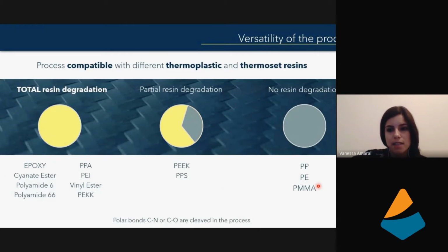Actually, what happens is that the chemicals are going to cleave the carbon-nitrogen or carbon-oxygen bonds in the matrix. So the process works very well. It's very compatible with epoxy resins, cyanate ester, polyamide, PPA, PEI, vinyl ester, PEKK, and other types of thermoplastic and thermoset resins. Using PEEK and PPS, we have to change a little bit the conditions, but we can still have